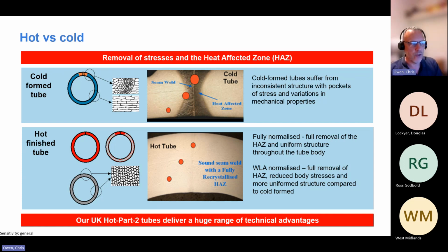We did a lot of work with Cranfield University and their corrosion science team, looking at the potential differences across the tubes, and obviously at the weld seam area. When you've got a cold form tube, you've still got that stress in place which initiates corrosion. Depending on whether the trimming of the internal weld bead has taken place or not, you've also got the risk of crevices which can result in crevice corrosion. And with a hot finish process route, you're removing that risk because you're removing that heat affected zone, by allowing that extra heat to be applied, which allows the grain structure to reorganize itself.